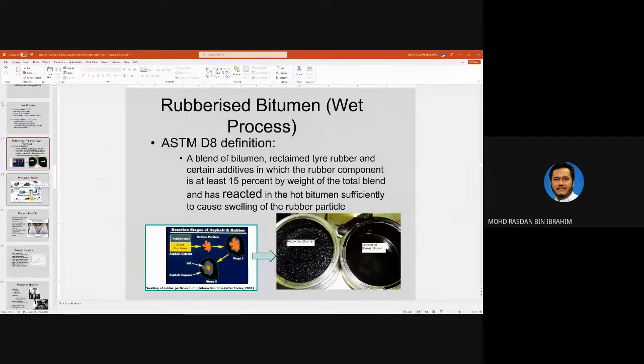So the standard that we use is ASTM D6114. The definition here: a blend of bitumen where the reclaimed tire rubber and certain additives is at least 15% by the weight of total blend and has reacted in hot bitumen. Okay, the trick if you want to increase the percentage of rubber, you want to use a higher rubber percentage, is you use larger particles. If you use smaller particles, you will never ever be able to achieve 15%. But if you really need to use 15%, you need to use larger particles, maybe around 1 millimeter, something like that.